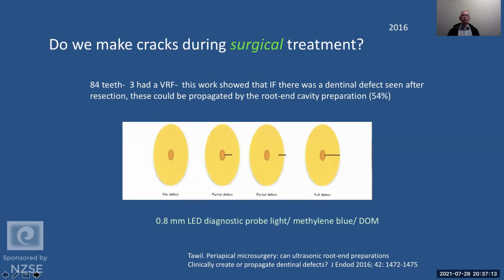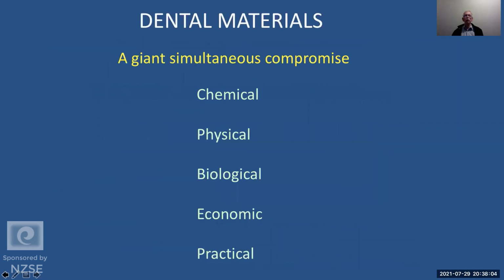And then having talked about cracks, do we make cracks during our surgical treatment? And here's a paper which showed that if they resected a root and found a defect on that resected surface and then cut their root end cavity, there was a more than 50% chance that they'd generate a big crack. So if there's something wrong at that root end and you then make the root end cavity, you're going to make it worse. And that takes us back to what I've just said about, can you see if there's a crack or not? And all of those disagreements that we had, even using the microscope, about cracks. So probably things aren't anywhere near as good at the resected root tip as we'd actually like.